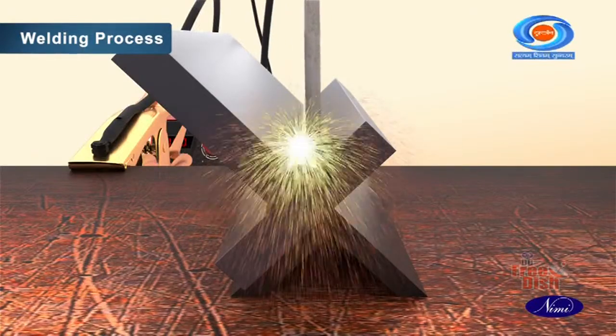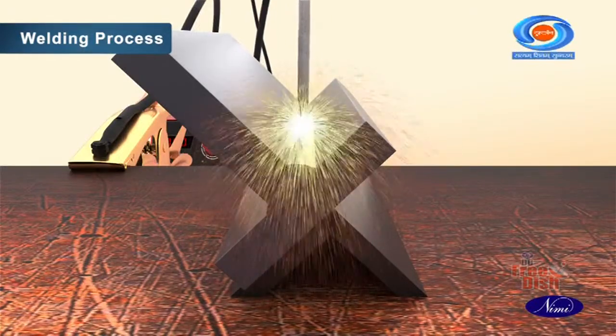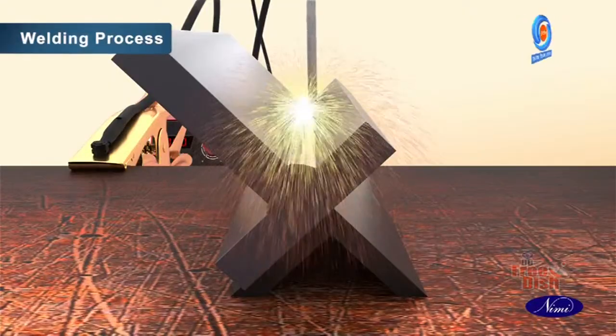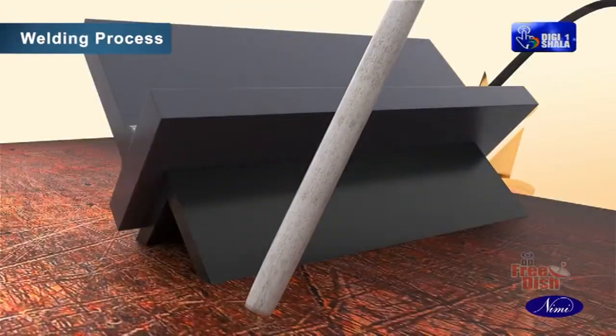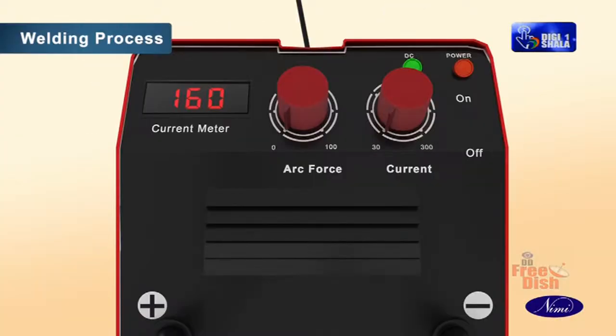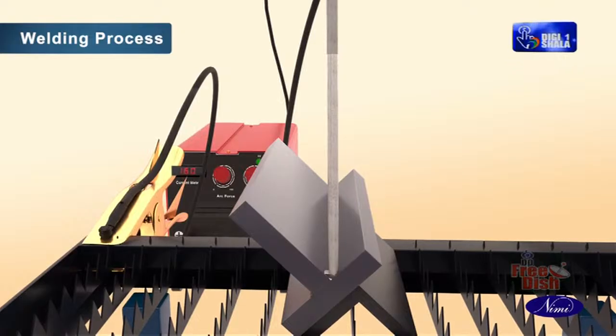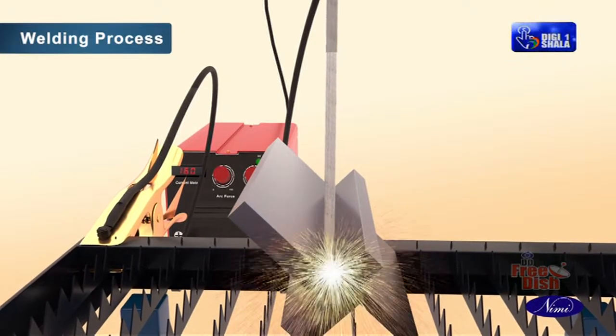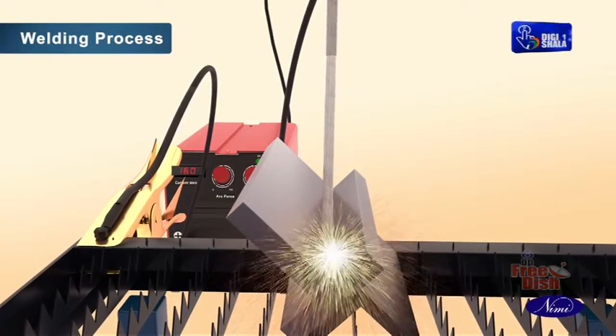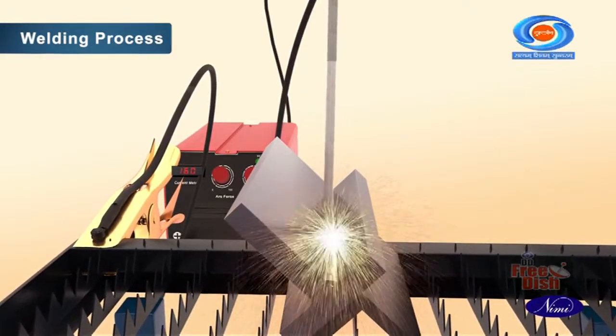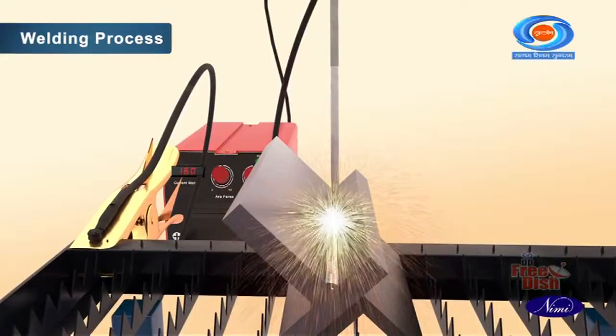Deposit covering run with a weave motion using a 4 mm dia medium coated MS electrode and 160 amps welding current. Proceed along the welding line with uniform travel speed and short arc to get uniform fusion and root penetration.